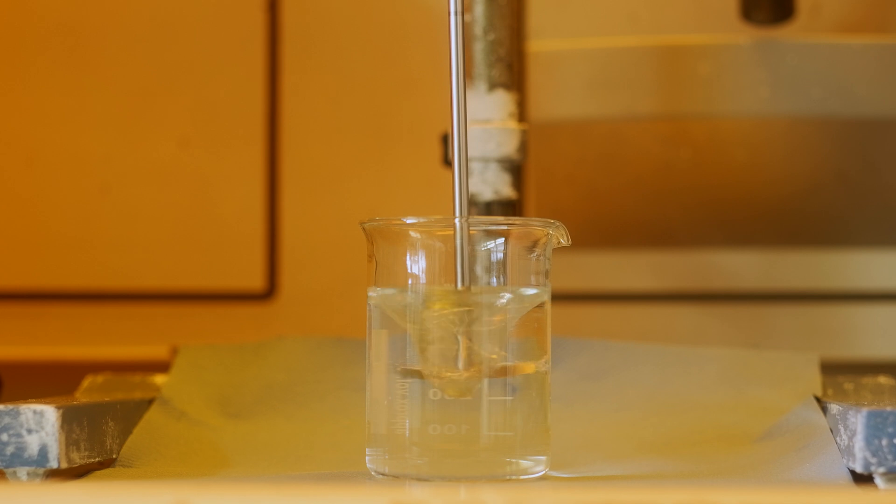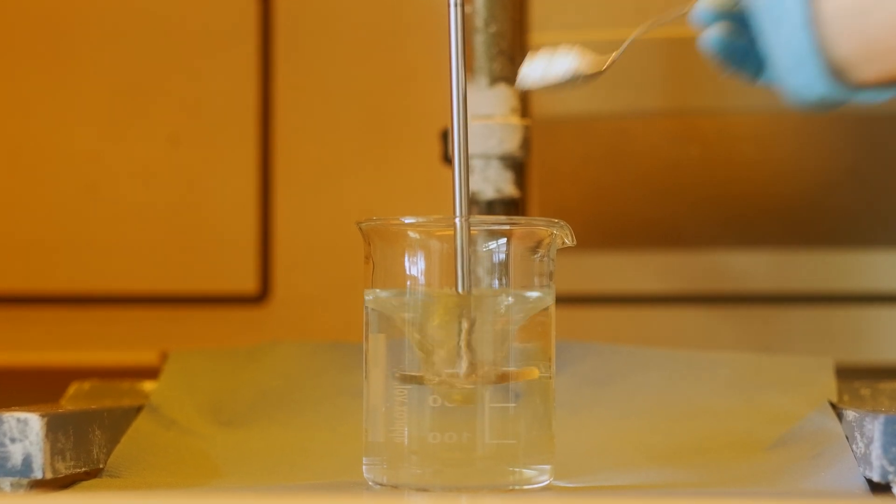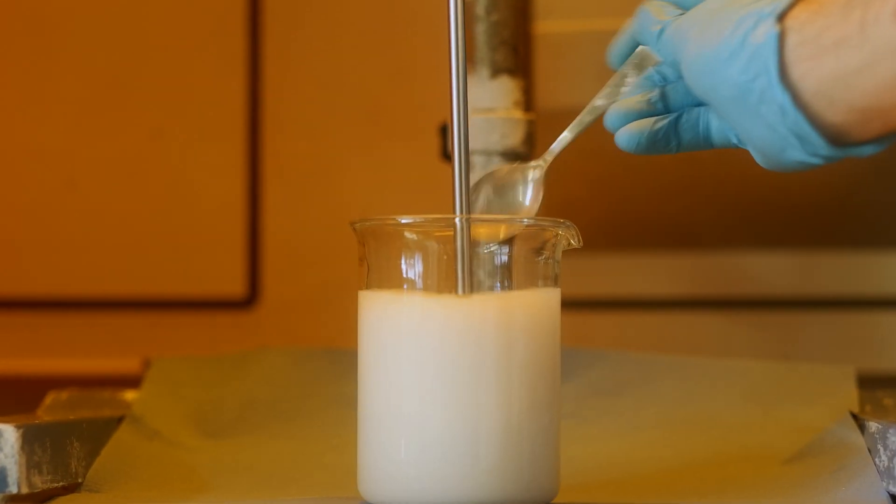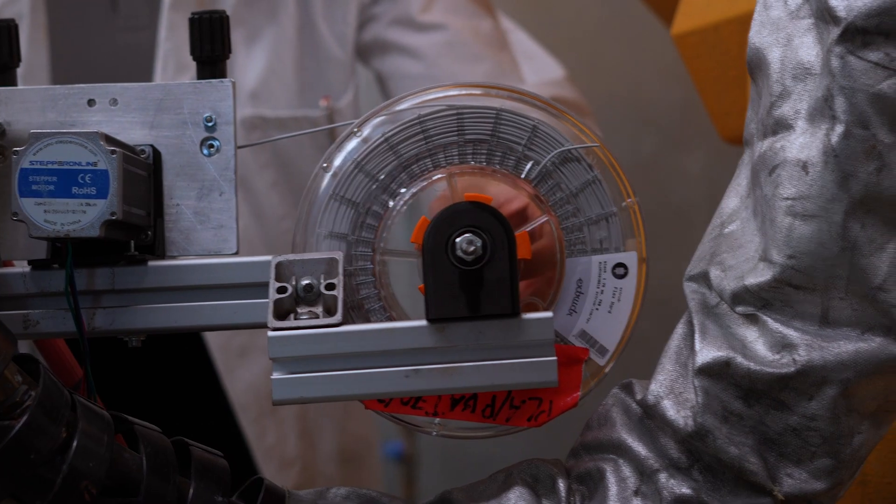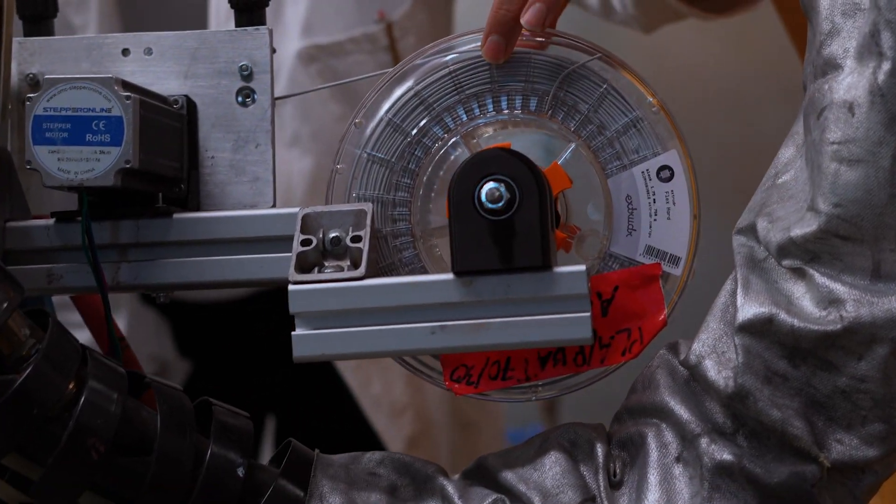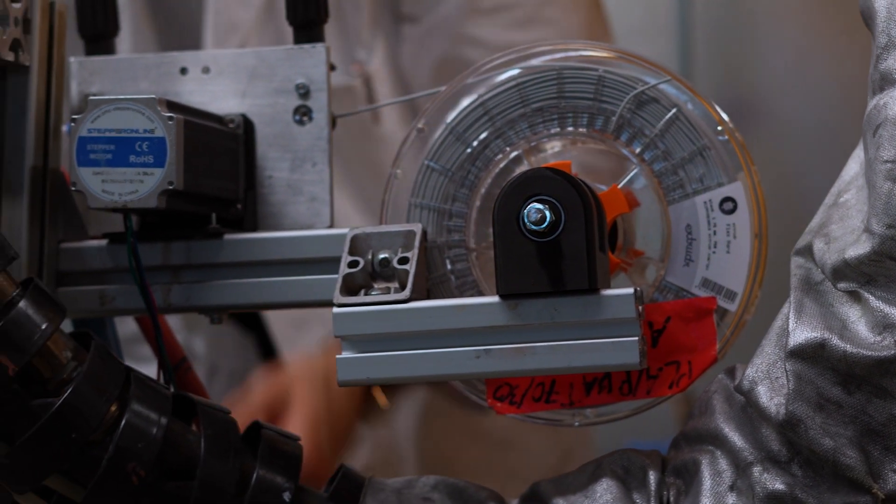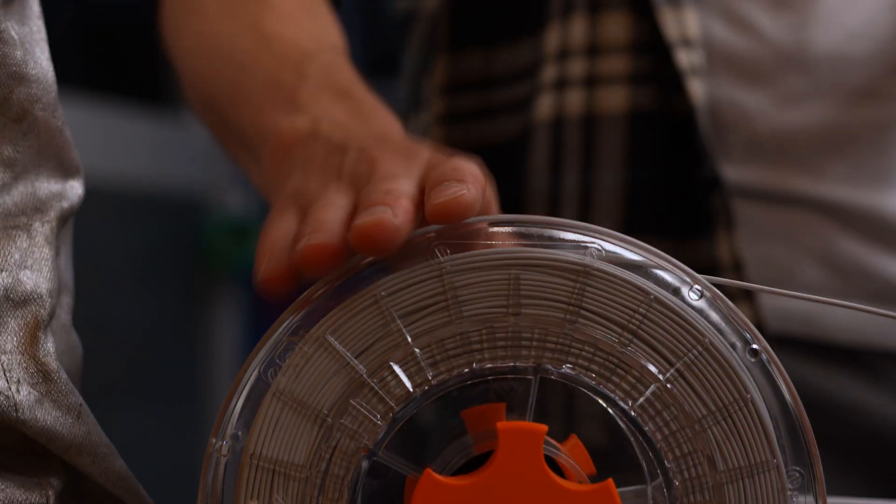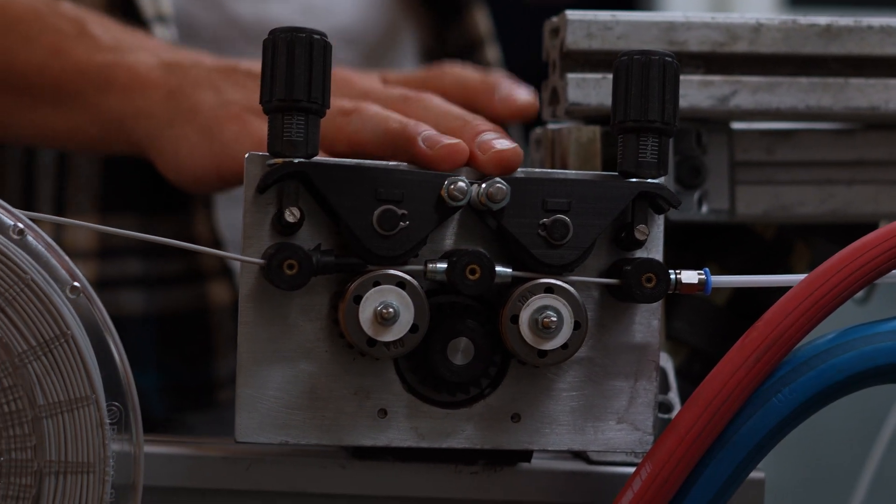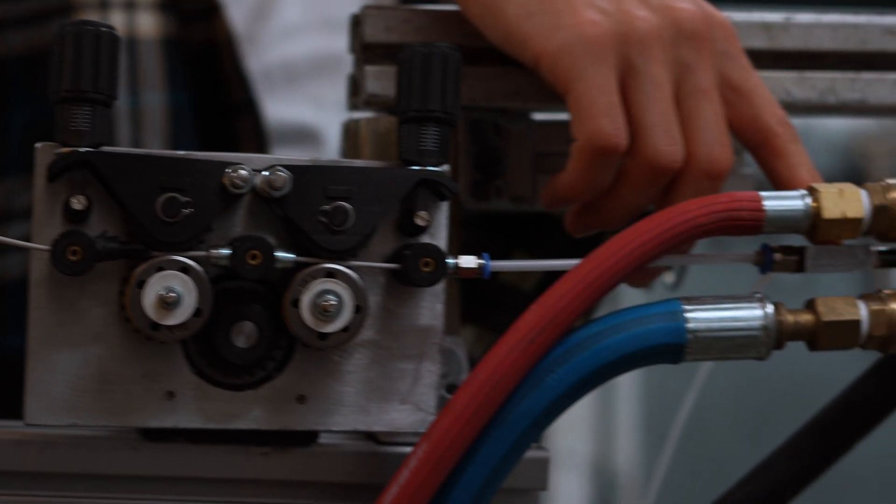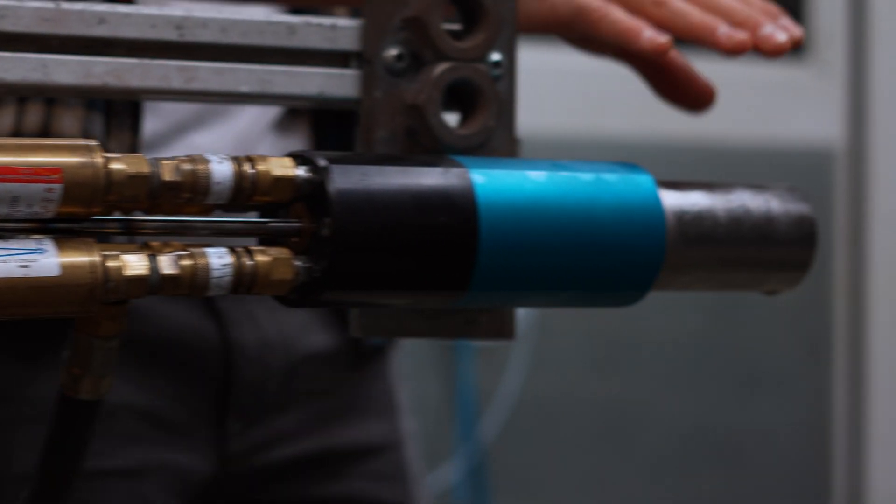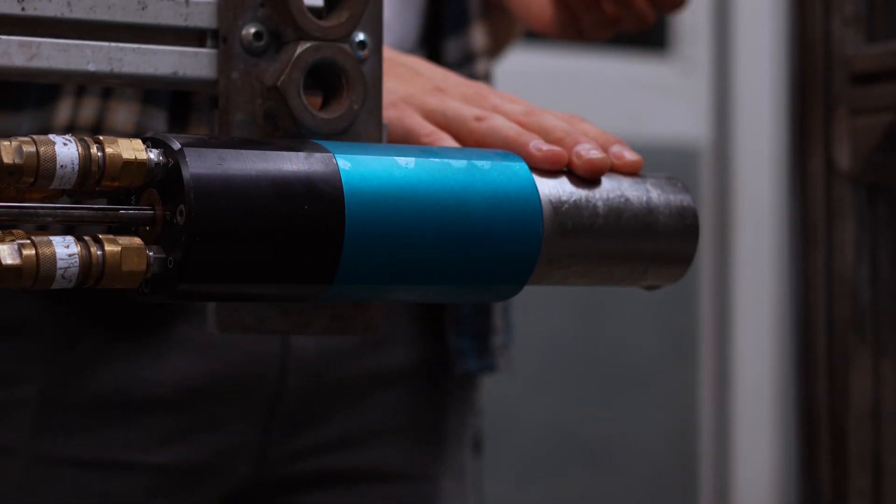So what we've done is we disperse our powder, it can be ceramics or metals, within our polymeric binder material, so the filament. And then we process it with the thermal spraying. Here we can see our setup. We've got the filament in the back and it's fed through a mechanical feeding system into our torch. In the torch we have a supply of ethene and oxygen which is burnt. It's basically like a strong flamethrower.